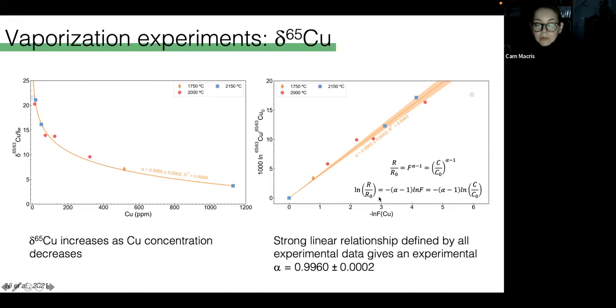If we take the natural log of both sides of this equation, we can get rid of that exponent. And now we have the relationship as the equation for a line, where the alpha, or the fractionation factor, is now embedded in the slope of this line. And so that's how we determine that we got an experimental alpha of 0.996 here.